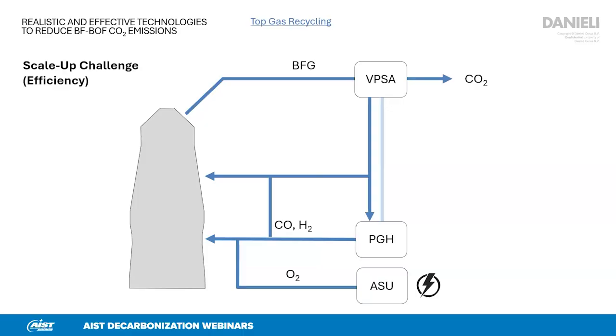It needs oxygen, which is made by an air separation unit, consuming electricity. It includes a process gas heater. It includes a CO2 scrubber. We've been assuming a VPSA. Excess CO2 is either emitted. We are not assuming CCUS. And the top gas would be recycled and injected also in the shaft to restore the heat balance. One of the main challenges in this industry is the scale up, because the scale up could have a dramatic impact on the efficiency of the top gas recycling scenarios. And until top gas recycling is demonstrated on industrial scale, we simply cannot reliably predict the efficiency of this technology. So we've been assuming, I would say, a moderate efficiency of top gas recycling as reported in the industry.